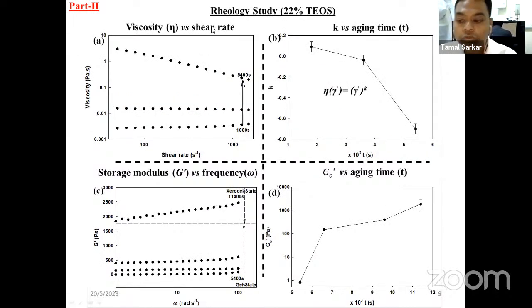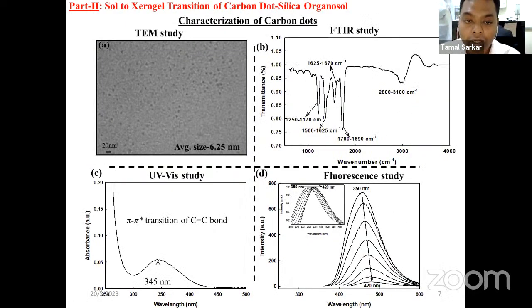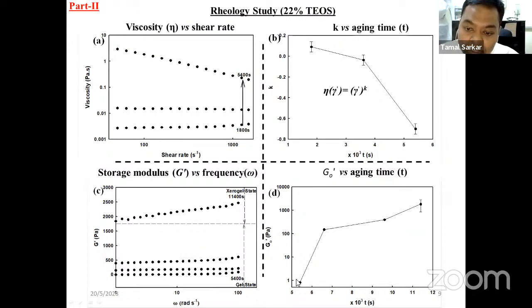A similar study is shown from the rheological point of view, where the viscosity is plotted with respect to shear rate, and the storage modulus is plotted with respect to the omega frequency of the shear, where again I showed that the G prime value increases. You could see the data sets are very few here because I took much less time to take data, because the sol became gel very fast. That is why I don't have much data in this region. As we can see, the G prime value again increases. That means when the gel state goes towards a xerogel state, the G naught prime value increases. The gel becomes rigid with time till it reaches the xerogel state.